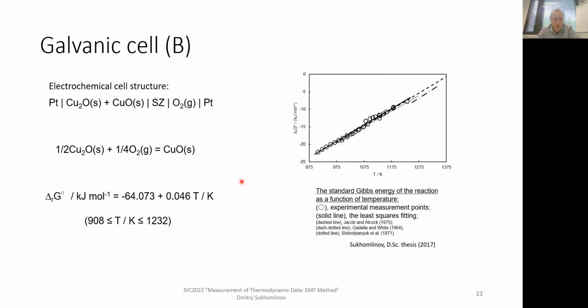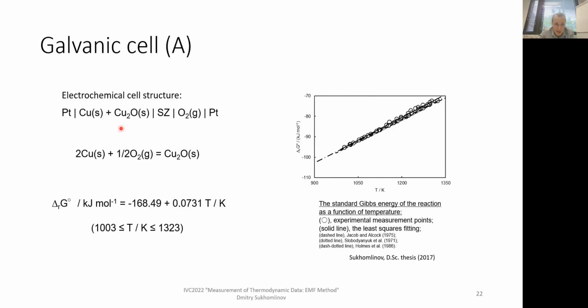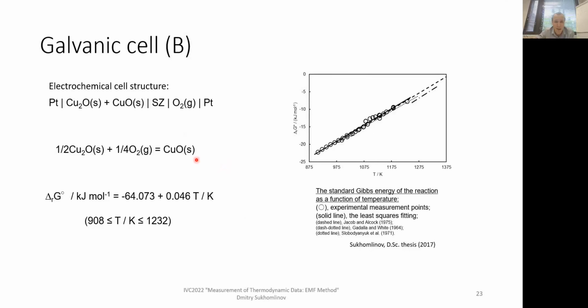Then reaction B. So we mix two oxides of copper, 2 plus and 1 plus, and a pretty similar measurement, also in rather good agreement. What I must emphasize, it will be explained later, is that this basically directly gives the energy of formation of CuO, but here it's another reaction. But having this delta G data and the previous one, we can also calculate the Gibbs energy of formation of CuO from oxygen and copper, just by combining them.